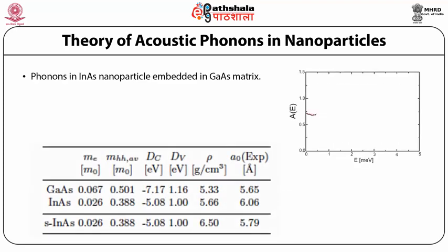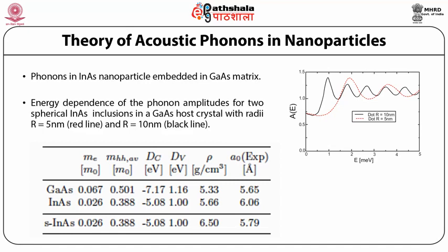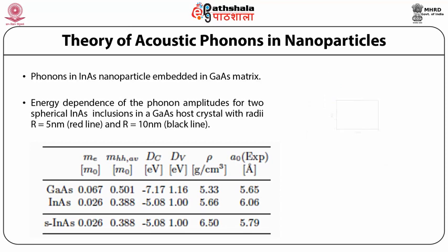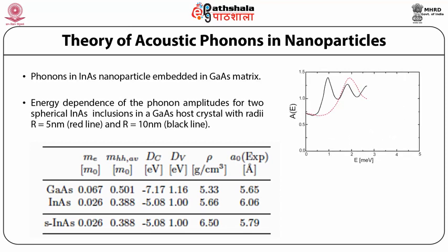Phonons in indium arsenide nanoparticle embedded in gallium arsenide matrix. This figure shows the energy dependence of the phonon amplitudes for two spherical indium arsenide nanoparticles with a radius capital R equal to 5 nanometer and capital R equal to 10 nanometer in an infinitely extended host lattice. The values for the different parameters used to calculate the results are presented in this figure and are also tabulated in this table, where the values of ME, MHH average, DC, DV, rho and A0 are given for gallium arsenide, indium arsenide and strained indium arsenide.